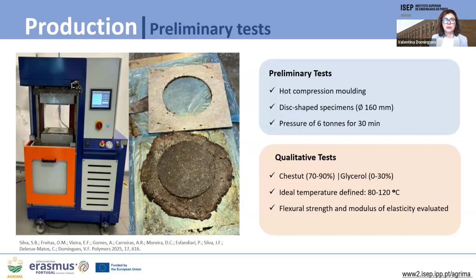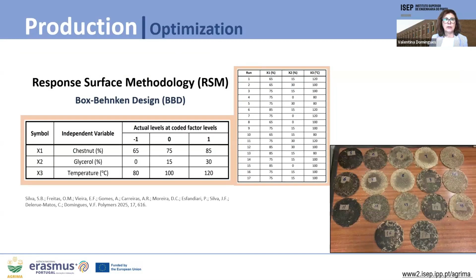And we evaluate the composites using two properties, the flexural strength and modulus of elasticity. So response surface methodology with Box-Behnken design was used to investigate the influence of the independent variables, which comprise the chestnut content, glycerol content, and molding temperature on the flexural strength and flexural modulus. This table in the middle shows the design matrix for 17 experimental runs. Each run was performed in triplicate, and here on the right, this is the picture of the 17 biocomposites obtained.